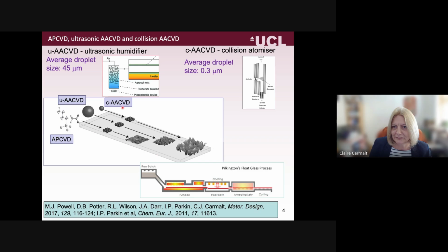This diagram is quite nice because it compares what sort of morphology you get from the different techniques. So there's APCVD here, where you just put the precursors into the gas phase, and you tend to get quite featureless morphology forming. Then there's one I've called UAACVD, where we use an ultrasonic humidifier to create the aerosol of our precursor solution. Now this actually forms quite large aerosol droplets, and so when that's used in AACVD, you get this quite textured morphology as shown here.